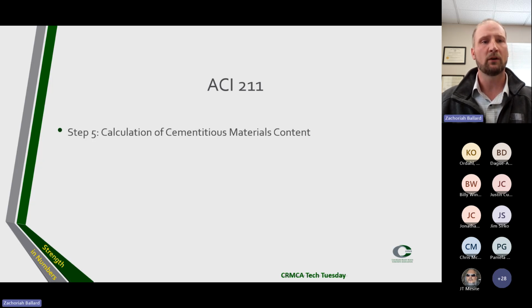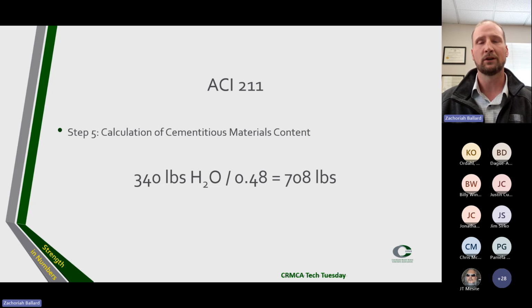Our step 5 is the calculation of the cementitious materials content. So we're going to take that 340 pounds of water, divide it by our water cement ratio, and we get a starting cement content of 708 pounds. The quantity of cementitious materials per unit volume of concrete is fixed by the determinations made in steps 3 and 4. If, however, we have a specification that includes a separate minimum limit on cementitious materials, in addition to the requirements for strength and durability, the mixture should be based on whichever criterion leads to the larger quantity of cementitious materials.